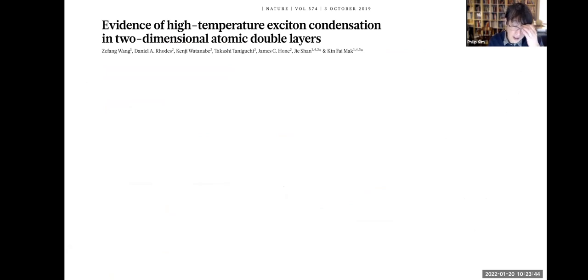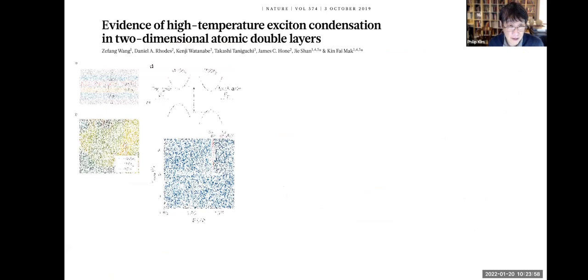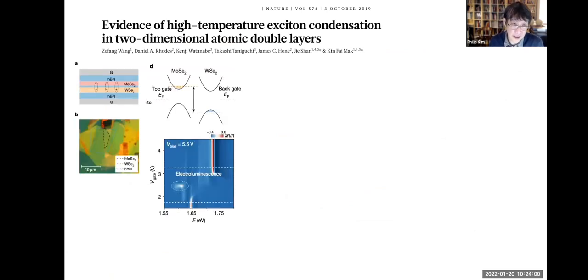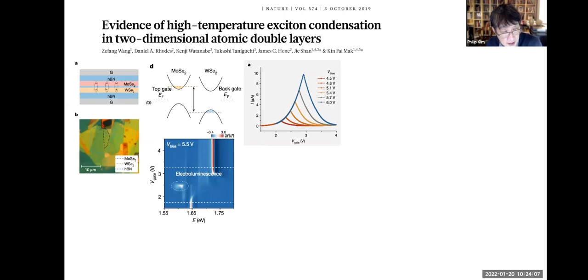The work done by Cornell's group, led by Kin Fai Mak's group, beautifully demonstrated that if you just insert an additional layer of boron nitride, you can make the interlayer exciton's lifetime even longer. And of course, here that interlayer exciton can be formed by electron-hole injection, as I mentioned. And then by just biasing, you can get the tunneling current. When the tunneling current is flowing into the system, they see light come out, although that is not the direct light coming from the interlayer exciton.